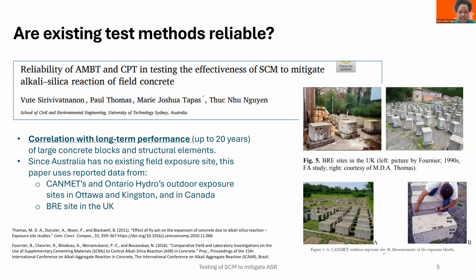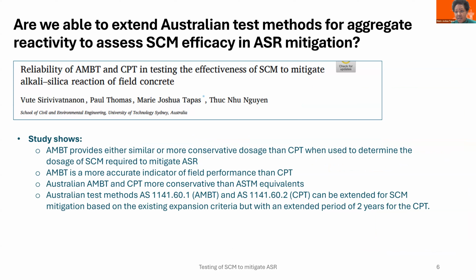And what we found is that the accelerated test methods actually have very, very good correlation with long-term performance data. In fact, the Australian test methods with their current test limits are conservative in comparison to the American counterparts. So the Australian test methods are exactly the same, basically, as international equivalents, except we have much more conservative test limits. And what we found is ours even correlate better. And in fact, AMBT, although heavily criticized to be a very aggressive test method, work better in terms of determining the dosage required for long-term mitigation of alkali silica reaction.